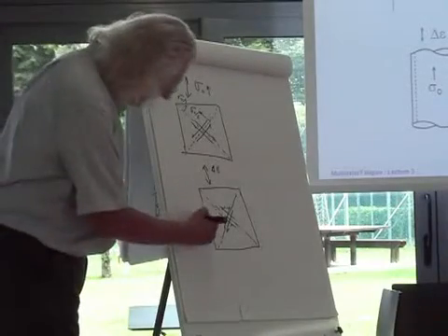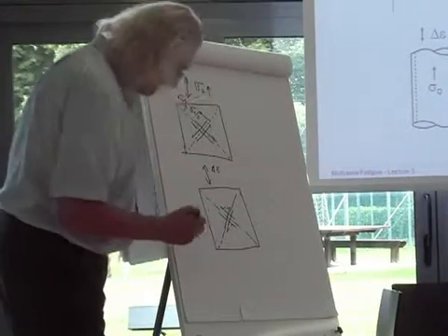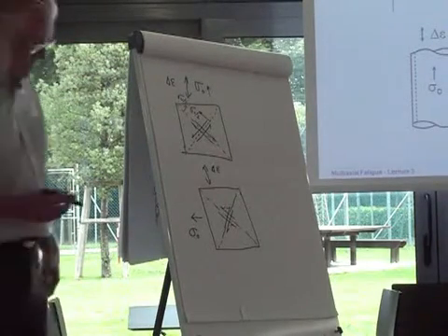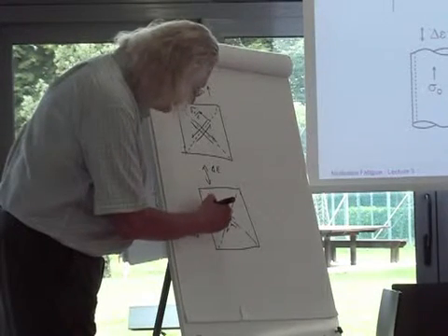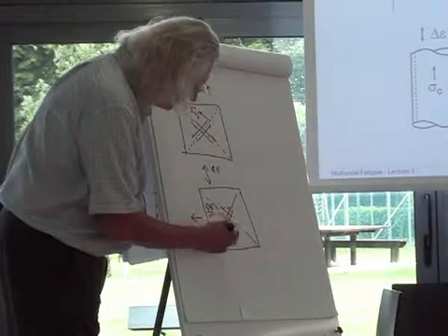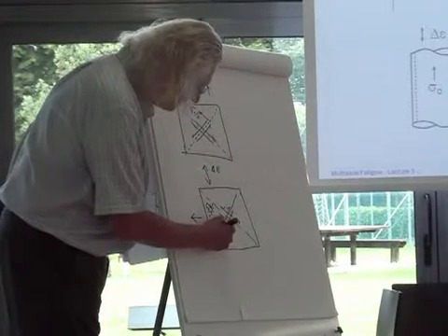And now, we put the mean stress there. Same magnitude as this one. And what's going to happen? Right? This is going to resolve into a stress on this plane of sigma 0 over 2, and it's going to resolve on a stress on this plane of sigma 0 over 2, right? For Mohr circle.